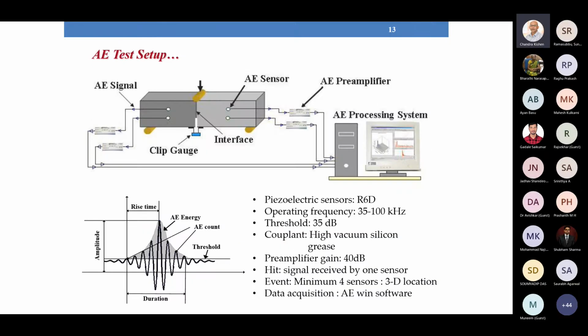So this is the setup of acoustic emission. These acoustic emission sensors are piezoelectric sensors operating in the frequency range of 35 to 100 kilohertz. We have used 8 sensors, and in some tests 6 sensors, 4 in the front and 4 behind. These sensors are connected through preamplifiers to a data acquisition system. This is a typical signal which we receive from an acoustic emission sensor, showing the duration and the amplitude. We set up what is known as a threshold of about 35 decibels, because for concrete a threshold of 35 to 39 works well. So anything below that, we don't analyze.